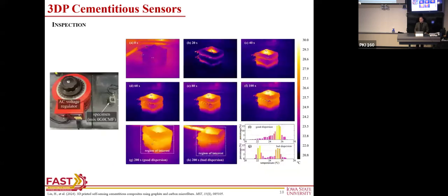A big question I get a lot of times from people in NDE is how do you make sure that your carbon or microfiber are well dispersed, especially if you're using nanotubes? You're not sure. In our case, what we do is we load the sensor with current. It heats up, and we look at the thermal dispersion as a function of time. So if your particles are well dispersed, you have this nice distribution of heat as you go up to here. If it's not well dispersed, you have this accumulation of heat at some level.